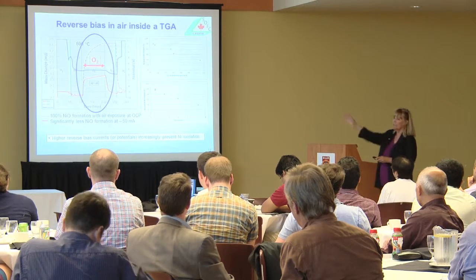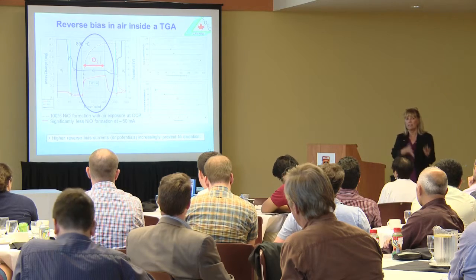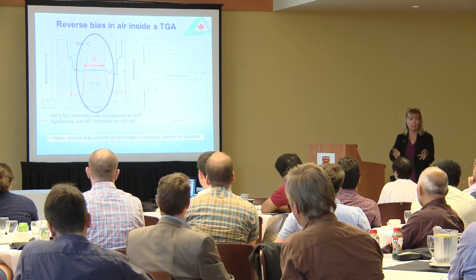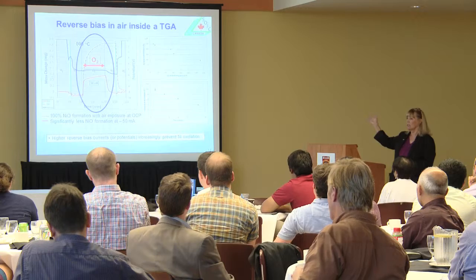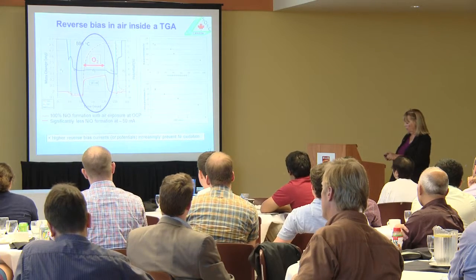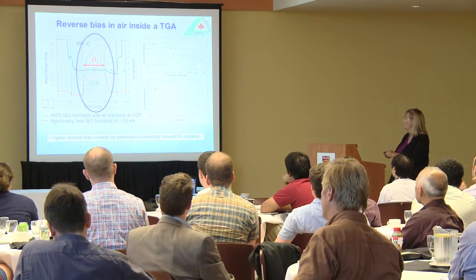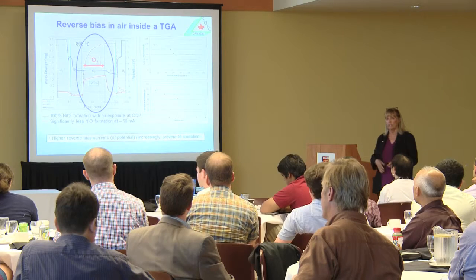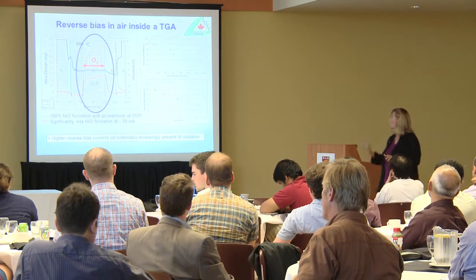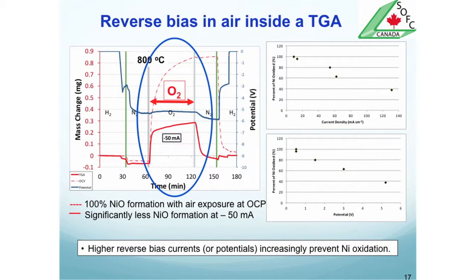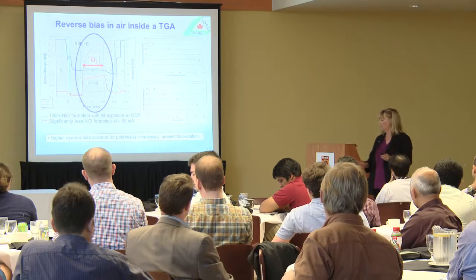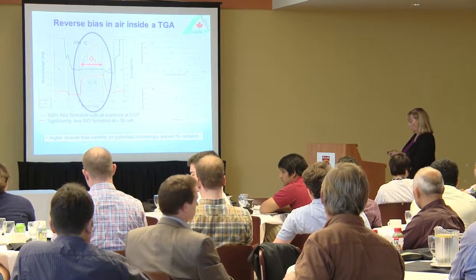And what you can see is the bigger the bias you apply, the less mass is gained by the nickel. Now, we reach sort of a semi-limit of about 40% protection. That's here. Beyond that, I think we have challenges, and we'll just leave it at that. But still, this is showing that we could potentially protect nickel from oxidation with a negative bias, maybe then being able to use oxygen in a useful way to strip off unwanted materials. Okay.